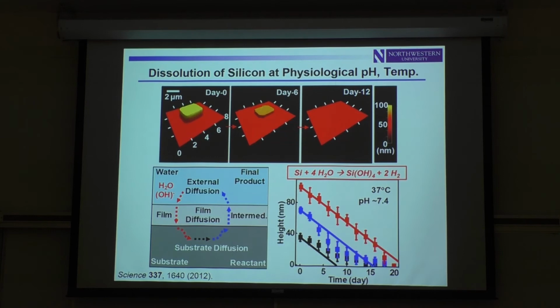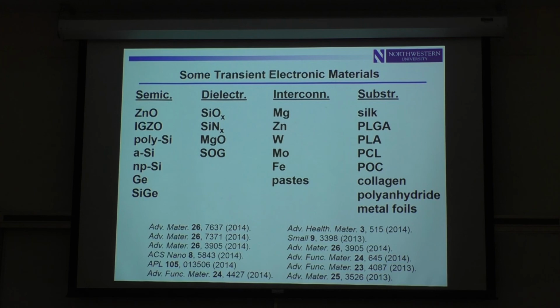So even ultra slow chemistry becomes critically important in the way you think about the material. This rate of reaction at physiological conditions will reduce the thickness of a silicon plate like that by about 2 to 3 nanometers per day. And so if you start with a 20, 30 nanometer sheet of silicon, that means it's gone in 10 days or so. And furthermore, silicic acid is a naturally occurring compound in the human body already. And so it becomes a very powerful and interesting semiconductor basis for bioresorbable electronics.